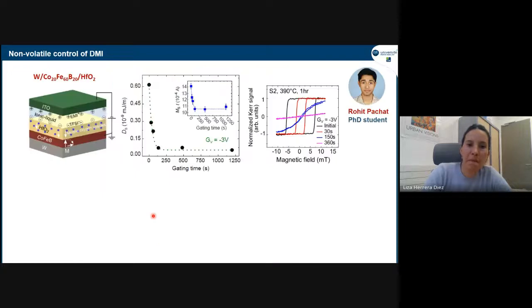So this here is a similar study. Here we have tungsten, cobalt, iron, boron, hafnium oxide, ionic liquid. And here we see a similar effect, the DMI reducing in absolute value as a function of the gating time. What is different from this system is that we had to anneal it to obtain PMA. So in this system, it's not enough just to pump oxygen to get PMA.